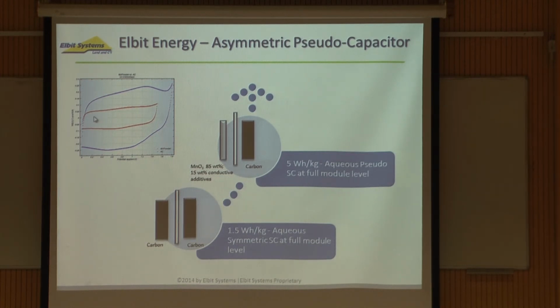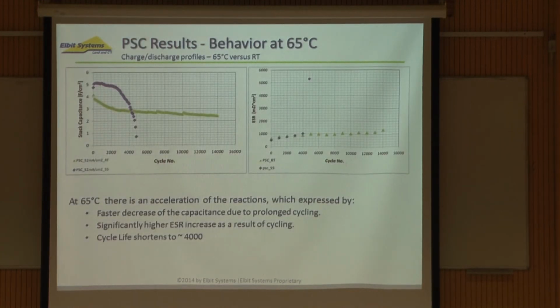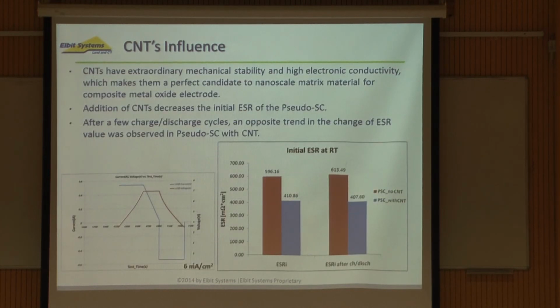This is the cyclic voltammetry, this is the standard symmetric configuration, and this is the asymmetric configuration. We did some acceleration tests in order to see what happens. We found out that when you have a supercapacitor without CNTs, there was an acceleration of the reactions, and you can see that after 5,000 cycles, it died. So the specific capacitance drops very drastically, and also the inner resistance increased very much. And then we said, okay, we will put some CNTs into the cathode.